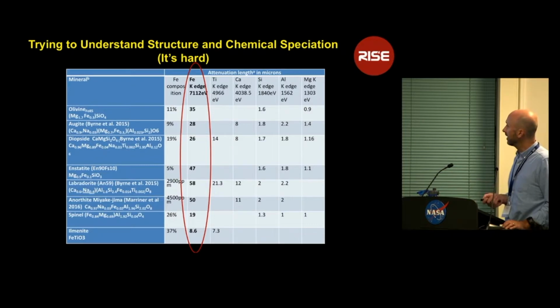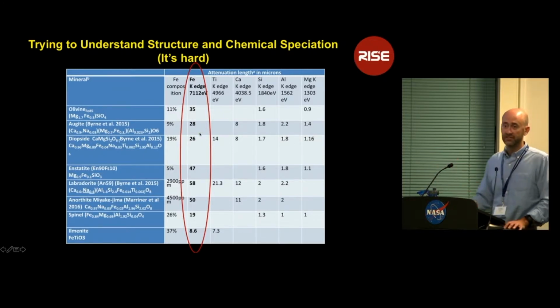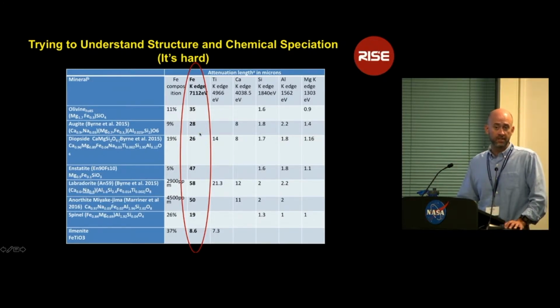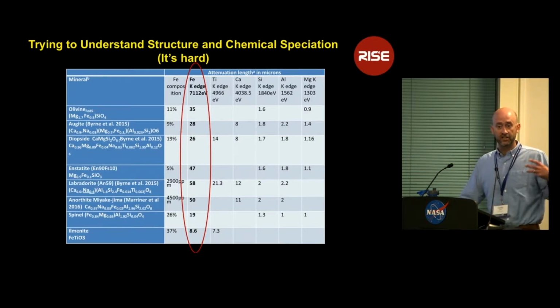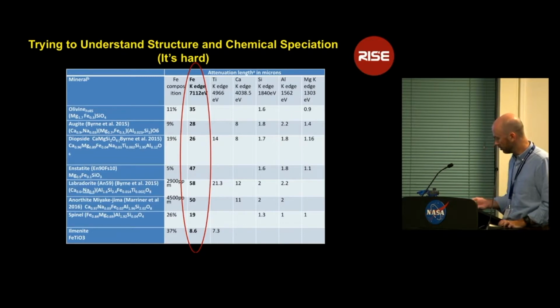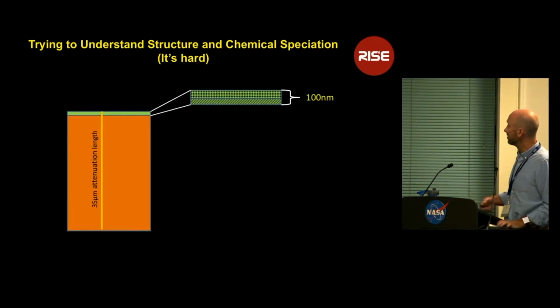If we're looking specifically at iron, one thing that we have to be very aware of is that for any given mineral, when we're looking at this iron K edge, the attenuation depth, basically the depth to which we're sensitive with the X-rays, is on the order of tens of microns, several tens of microns. And so if we're looking, say, for an oxidation state change in the very upper surface, that signal is going to be drowned out almost completely by the bulk sample. So we have a way, we think, to try to get around that.